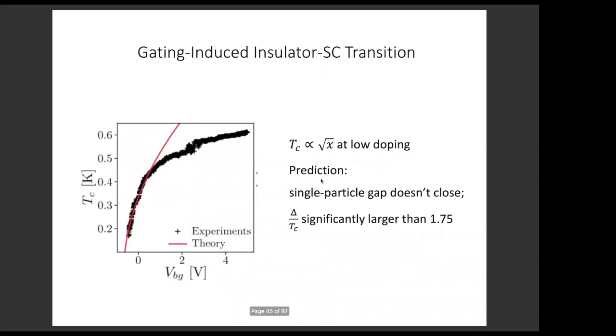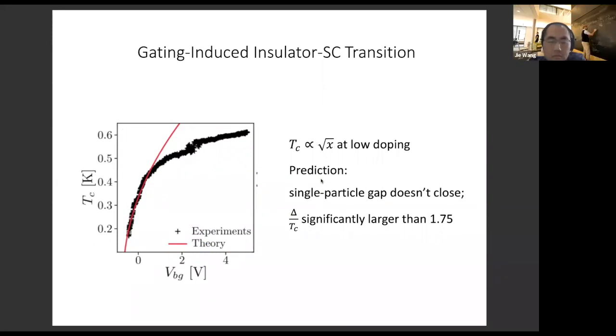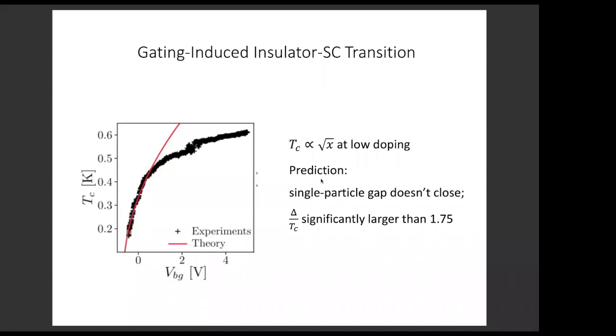So one thing we compared is our theory with experimental data from Pablo's group, Tc as a function of the gate voltage, which is proportional to doping. And we do see that at low density, the Tc rises as a square root of density. This is again unusual because in the BCS framework, we would expect that in 2D systems the density of states is constant, independent of energy, and BCS theory says Tc is controlled basically by the density of states. So you would expect that Tc is nearly independent of density. While in all these theories that I've described, as well as in cold atom systems, the pairing interaction is not limited to the vicinity of the Fermi level. For that reason, the Tc would have a strong density dependence, and it should go as the square root of density. This is a very robust result, and it matches nicely with experiments.